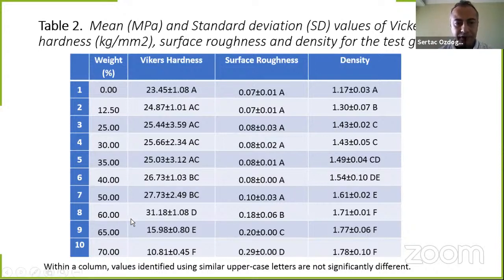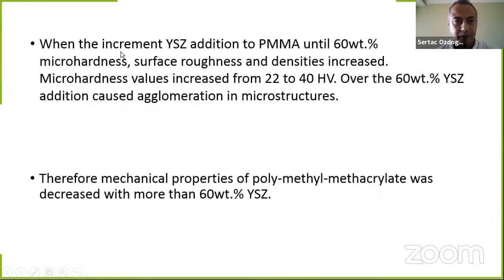Through the 60%, Vickers hardness and surface roughness increased, and then additions above that decreased the values. And we can say that when the yttrium zirconia addition to polymethyl methacrylate increased until 60wt.%, micro hardness, surface roughness, and densities increased. Micro hardness values increased from 22 to 40 Vickers hardness.